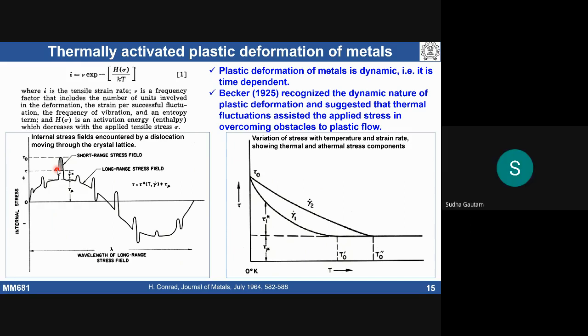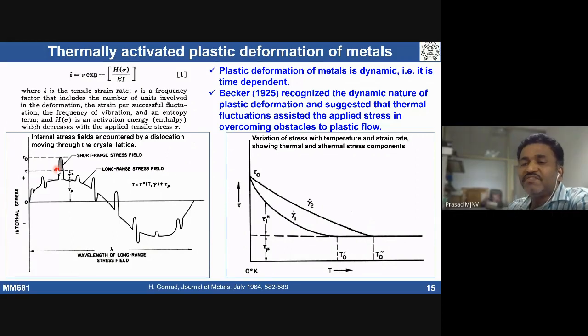Precipitates, intermetallics. Yes, if we have any precipitates of size greater than 10 atomic diameters, incoherent precipitates, when the dislocation is coming and sees a precipitate, it's going to stop for a while. We need to apply high stress to overcome that precipitate. So that is an example of a long range stress field, an athermal barrier.